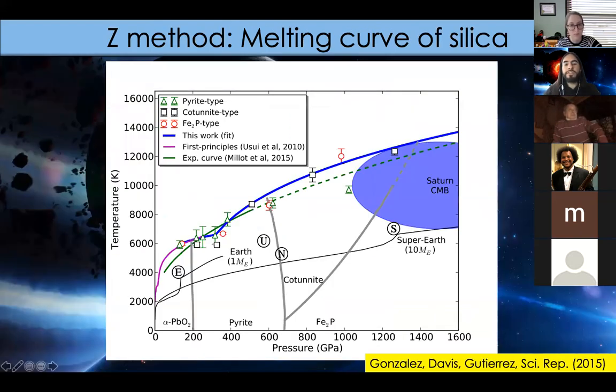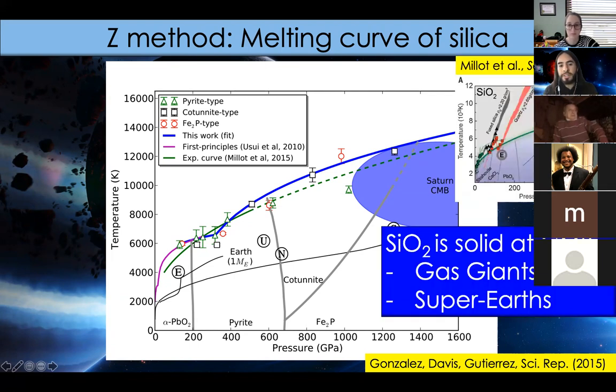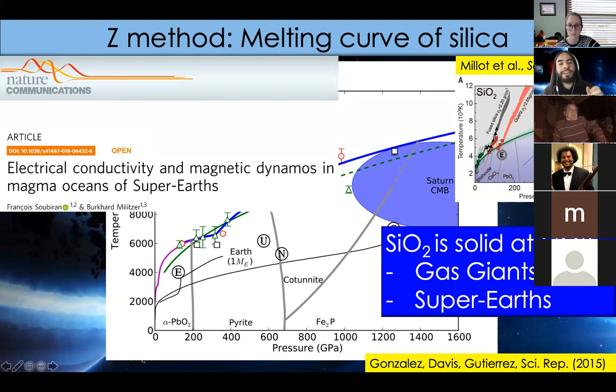We have used several methods in the past, like this Z method, to calculate silica, for example, once again, this mineral that is important for planetary science, and found that silica is solid at the conditions of the core mantle boundary of Saturn and Jupiter, and also solid for this interior of super Earths. And experiments have validated this melting curve. And they also found that the liquid that you obtain when you melt silica is conducting. And remember, other simulations that we've performed indicate also that other silicates are also electrical conductors. So it adds up to this idea that super Earths could be generating magnetic fields from the mantle because they become electrical conductors.